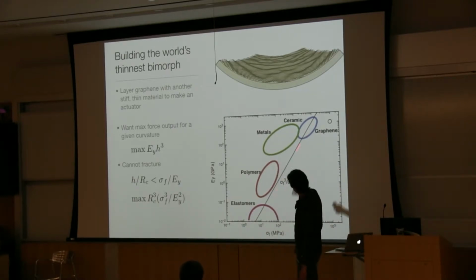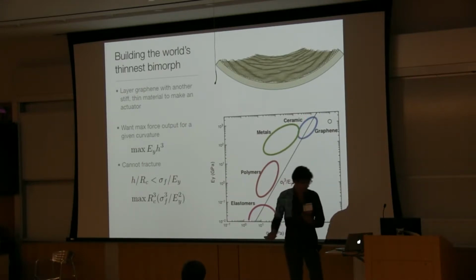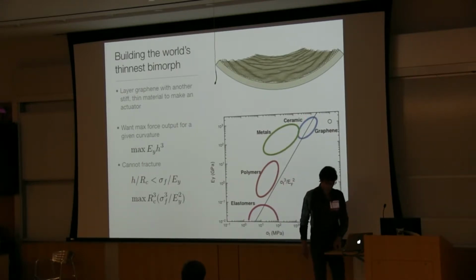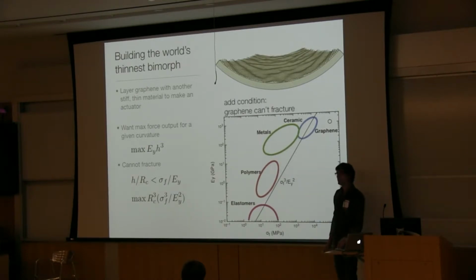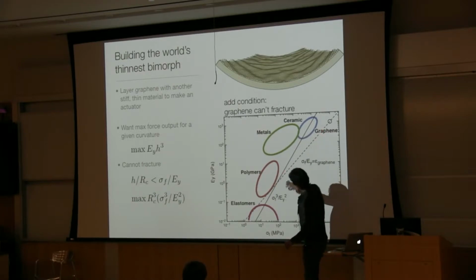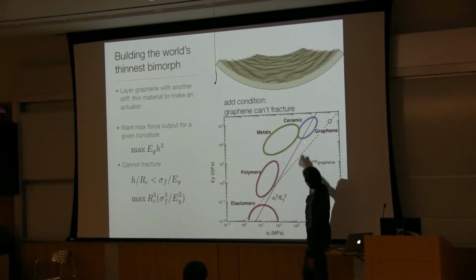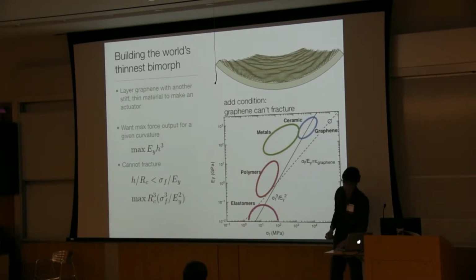And now we're left with just picking between two other things for a second layer in the actuator, and that's between ceramics, so things like glasses, and elastomers, things like hydrogels. Now, if we put in one extra constraint, which is that the graphene can't fracture, it also has to be elastic, then we need materials that live below the fracture strain for graphene. And that essentially rules out elastomers and leaves us with one set of materials that are going to give us our optimal choice, ceramics, so glass. And so for our first prototype, that's what we built.